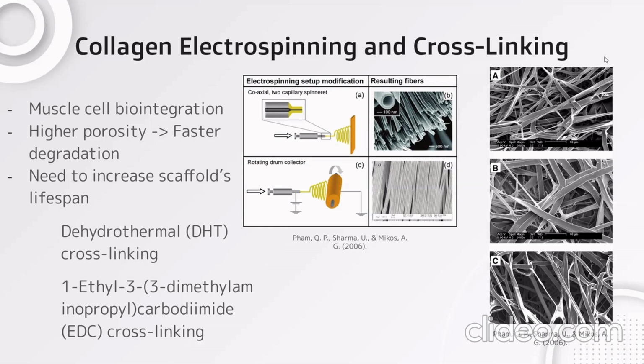This process basically turns the proteins or polymers from just a solution to a long, continuous, woven strand. And we use this woven strand of collagen to create an electrospun collagen mesh. In one past study, researchers used one of these meshes and seeded it with muscle cells, and it showed a high degree of biointegration and proliferation after a few days.